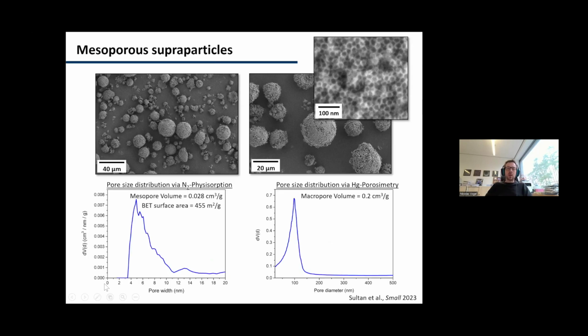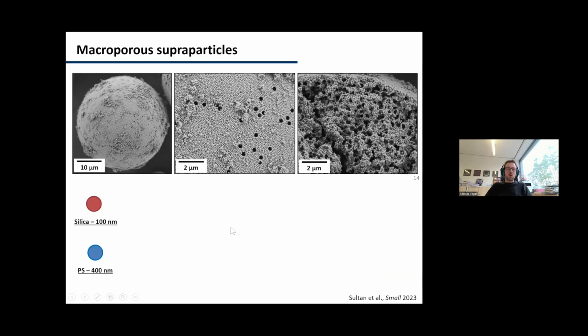And of course, if we then measure the pore size distribution, we see that we have smaller pores from the primary particles and the larger pores from the interstitial particles. Well, and then we can also add larger macroscopic particles. Here's just an example where we add a few larger polystyrene particles.